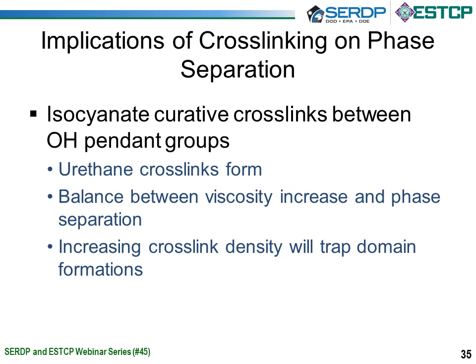In addition to that, we knew that phase separation occurs of the polyol. But what would happen once we started to cross-link these polyols with the isocyanates? We knew that we had to be very careful because there was a delicate balance between the increased viscosity that we would observe from the additional cross-linking, and yet phase separation we wanted to incur as well. So by increasing the cross-link density, we were able to trap the domains in place, and as you will see, this greatly limited the mobility in the curing process.